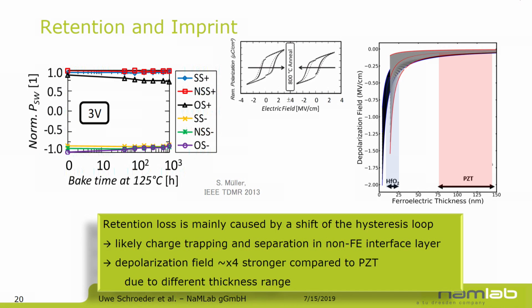Retention and imprint. As you can expect, I mentioned the 2 different coercive fields. For PZT, it was a little more critical, due to the low coercive field, to get good retention values. For the hafnium oxide, this is not that critical. Typically samples are polarized in one direction, then heated up, in this case to 125 degrees C, and then you look at the polarization or the opposite polarization of the material and check how stable retention is. And you can see for same state polarization that it's quite stable, and you see a drop here for the opposite state retention.